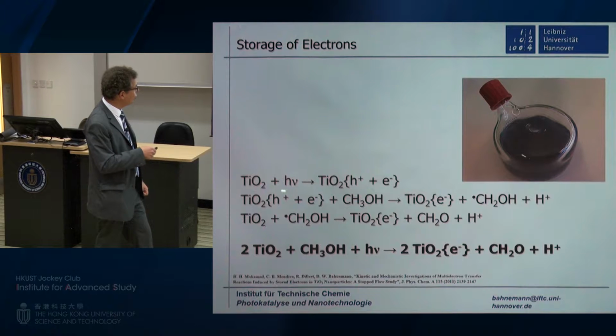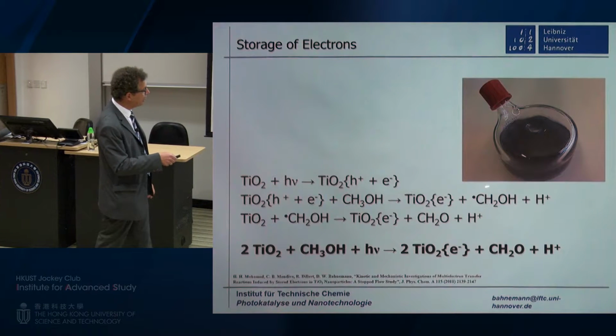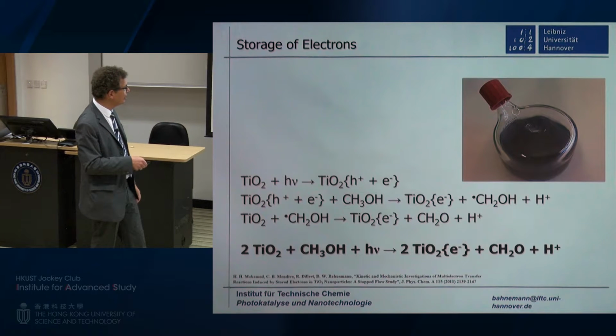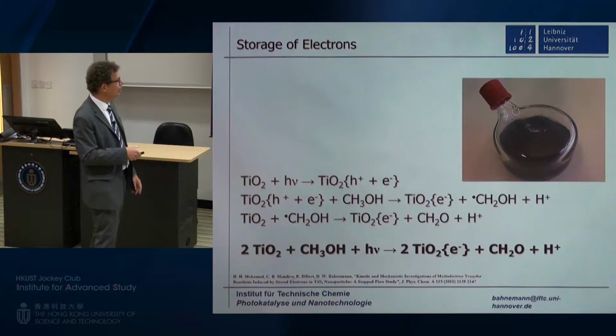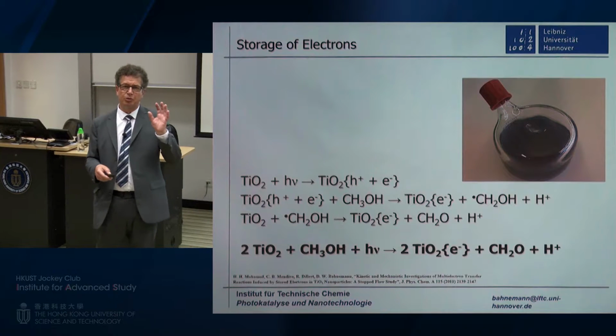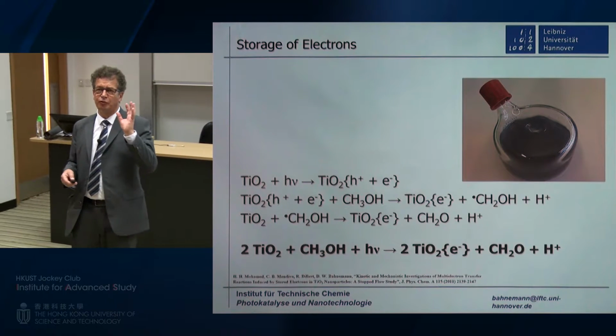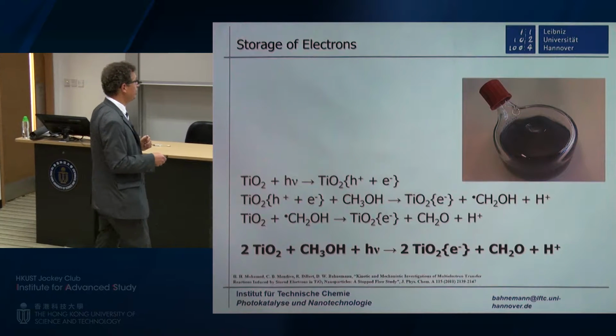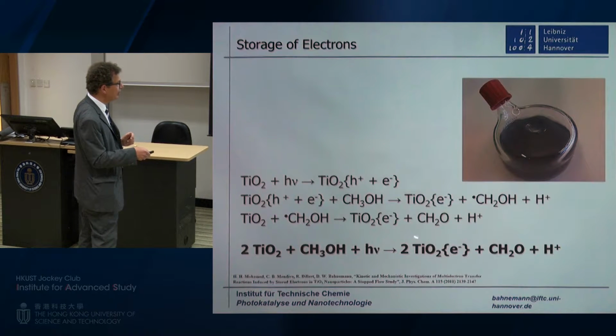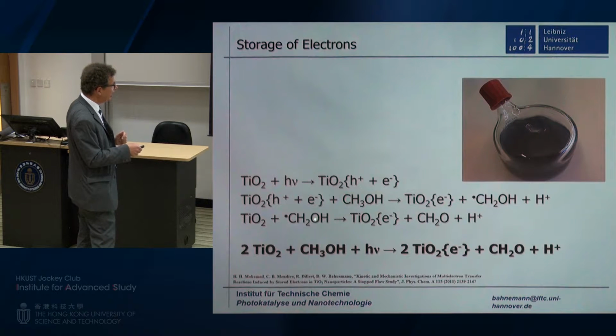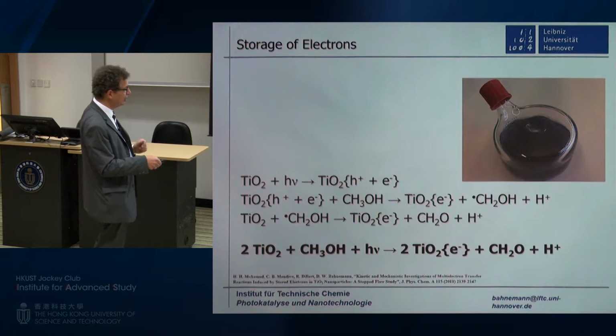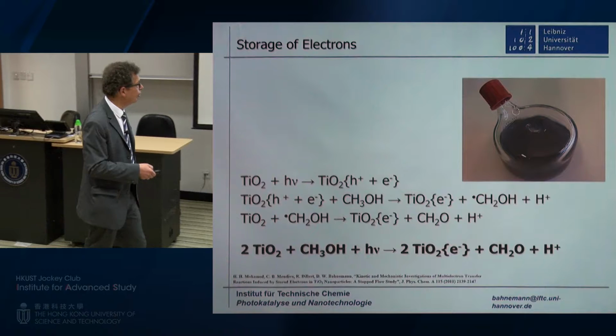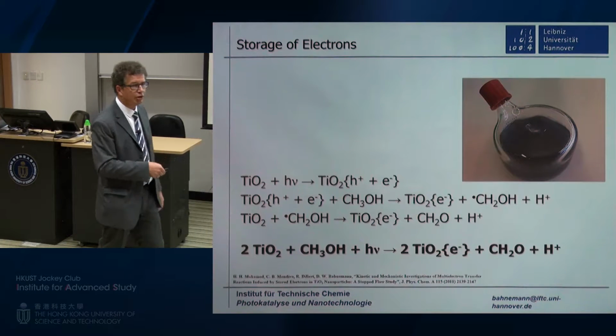When it gives away an electron to fill this hole, then at the same time you form this alpha hydroxymethyl radical. This is a very strong reductant with a 1 electron redox potential of about minus 1.4 electron volts. Very, very strong reductant indeed, because it wants to become formaldehyde. So it gives away another electron. So TiO2 gets a second electron. So overall you have a reaction where one photon generates 2 electrons in your TiO2 plus formaldehyde as the chemical product. And what you see is a blue coloration.